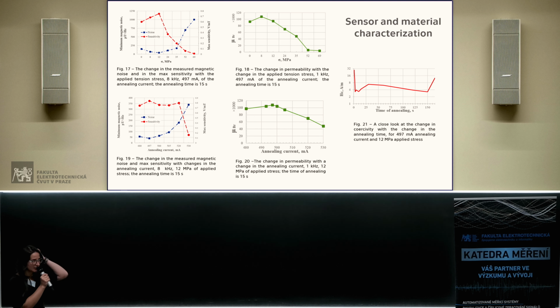And here are some results of magnetic characterization of the material. Here is a comparison of different results of annealing under different conditions, under different current, and when we apply different current, it's a different temperature and different stress. So you could see that after some point of applying stress, permeability is increasing and then decreasing, and for temperature it looks similar, but the characteristic is a bit flatter. So applied stress is really important, and also